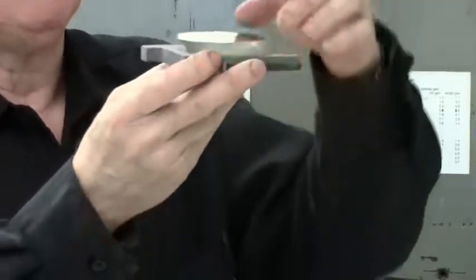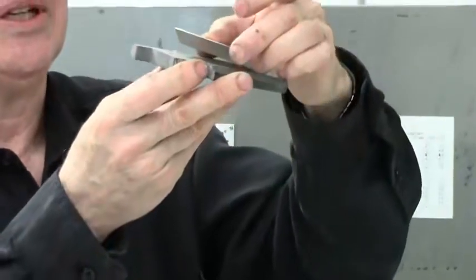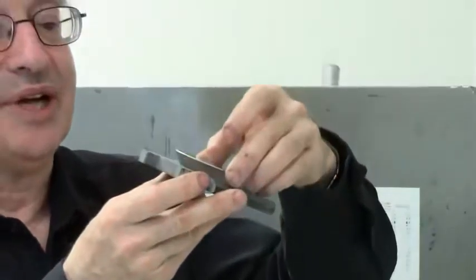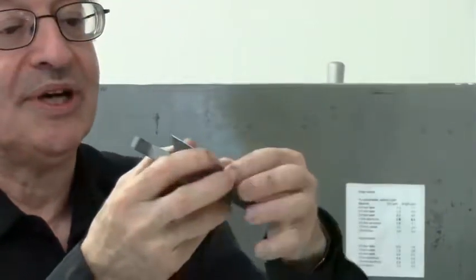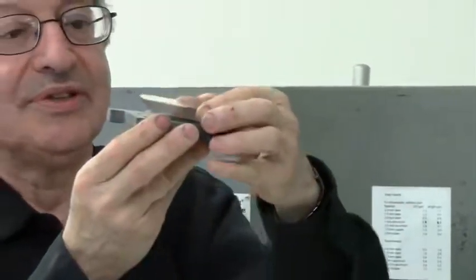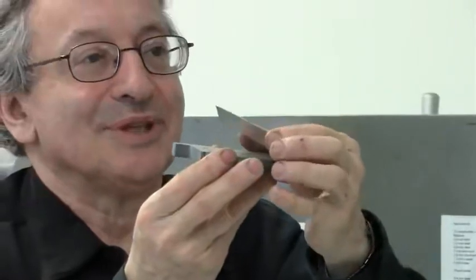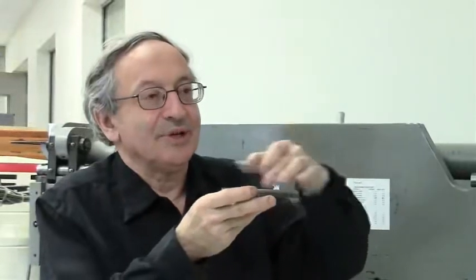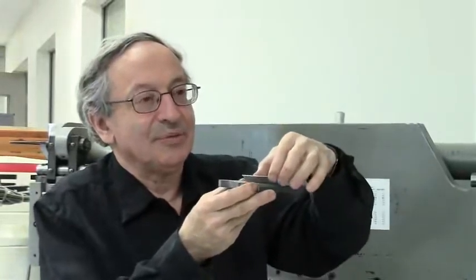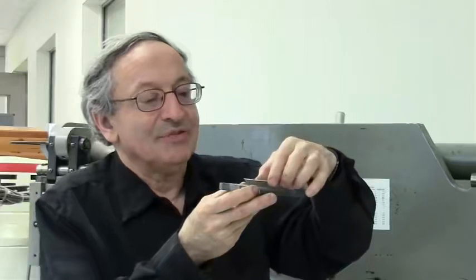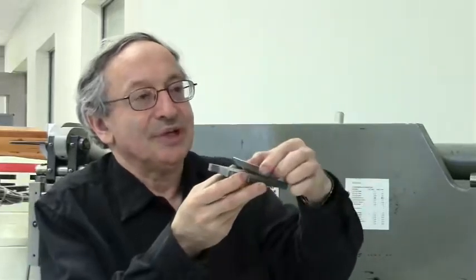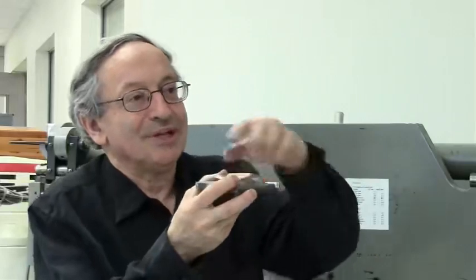But if you bond it and you fill the adhesive as a wedge, let's say you want to align it, and you align it and then you put epoxy behind it, which forms a wedge, then the angle of the mirror will change with temperature, and you have a big multiplier effect because of the optical lever. And it's true not just for a mirror, it's true for any structure you bond. If you bond a right angle bracket, as long as it's parallel, it will move up and down a bit, a few microns. But if it's a bracket which is bonded with a wedge, it will tilt, and the error will be multiplied by the length. So that's something to keep in mind.